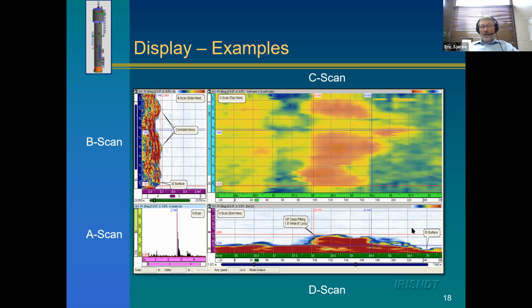And then the B scan and the D scan are cross-sectional views. So that's where those red cursors are. That just shows a cross-sectional view of the wall thickness of the pressure vessel at that location. And this is data that's good for engineering. So this is perfect for fitness for service.